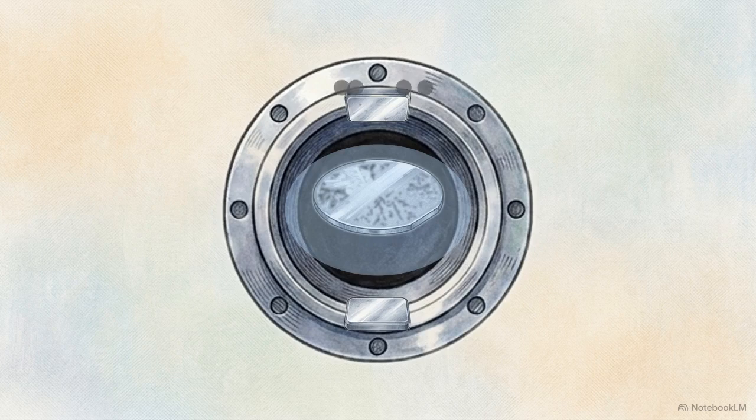The plasma contains two distinct agents. First are the neutral radicals. These are the chemical actors. They diffuse to the surface of the wafer and react with the silicon to form volatile byproducts that can be pumped out of the chamber. Second are the positive ions. These are the kinetic actors. The plasma sheath accelerates these ions in a strictly vertical direction, delivering the physical energy required to break the crystal bonds at the bottom of the trench.